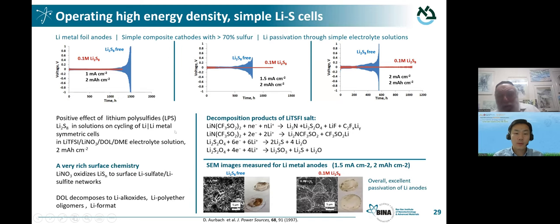It was all published, so it's possible to follow us with the publications, but it appears that here we have another very simple magic additive, just it has to be a priori in the electrolyte solution, so it will be affected by the lithium nitrate. And then we understand all the complex surface chemistry that can be developed here. All the components are reactive on the lithium surface, but they work synergistically to provide good passivation.